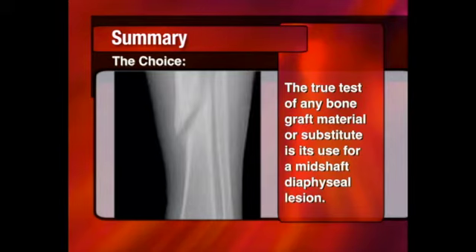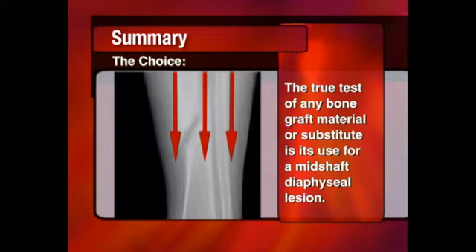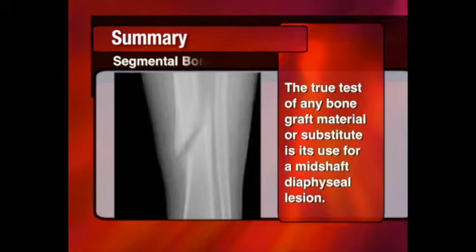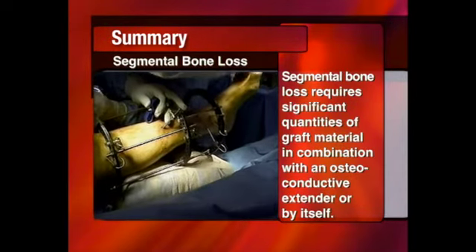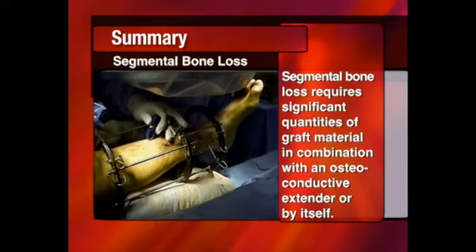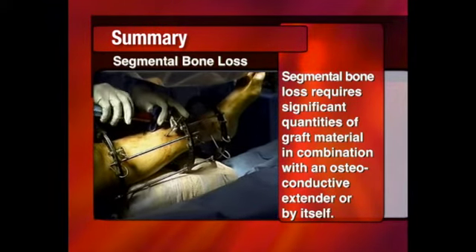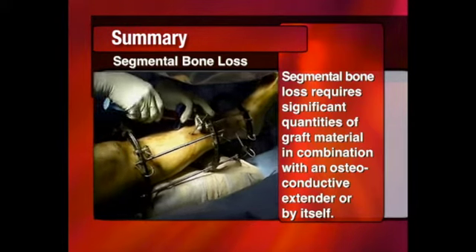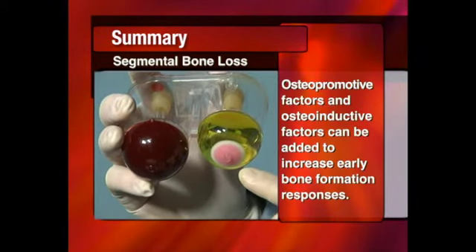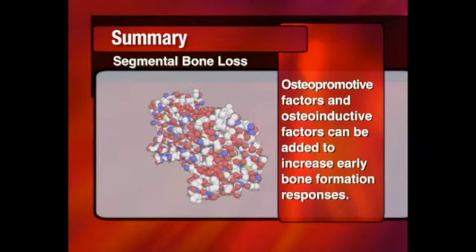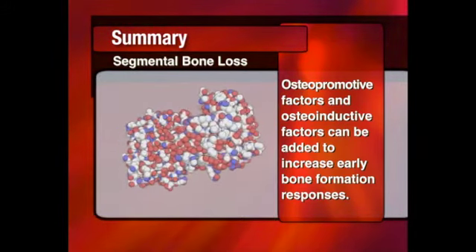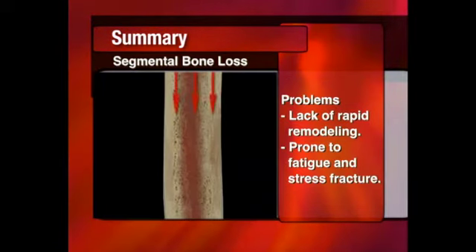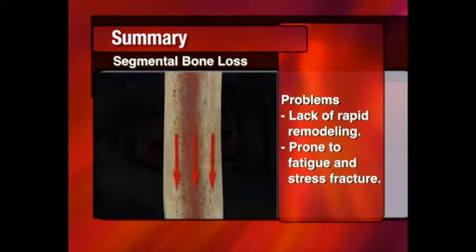The true test of any bone graft material or substitute is its use for a midshaft diaphyseal lesion. Segmental bone loss remains problematic and usually requires significant quantities of graft material in combination with an osteoconductive extender or by itself. Osteopromotive factors, such as those found in PRP and osteoinductive factors, such as recombinant BMP or those found in DBM, can also be added to increase early bone formation responses. Problems here include the lack of rapid remodeling. These defects are prone to fatigue and stress fracture.